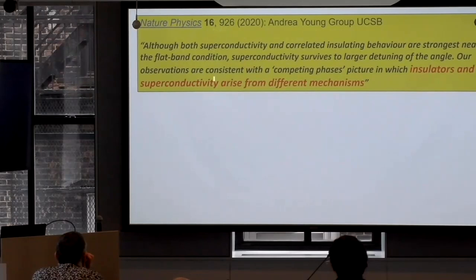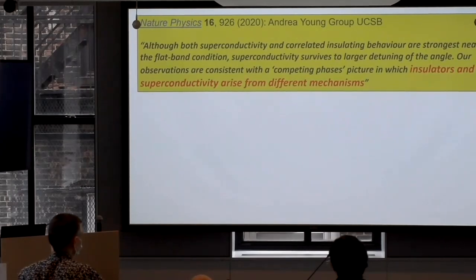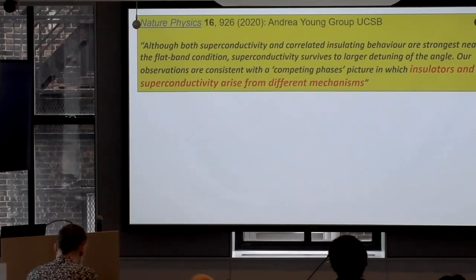Recently, several papers have come out. This is one paper. What they do, they take this graphene and you have gates on two sides. And this was an early suggestion. If you now apply gate potential to increase or decrease screening, for example, you can put the gates very far from each other, or you can bring them very close to each other, or you can apply electric field. So if it's electron-electron interaction generated, then when you reduce screening, superconductivity should be enhanced. When you increase screening, superconductivity should disappear. Well, exactly the opposite happened. So this is one paper.